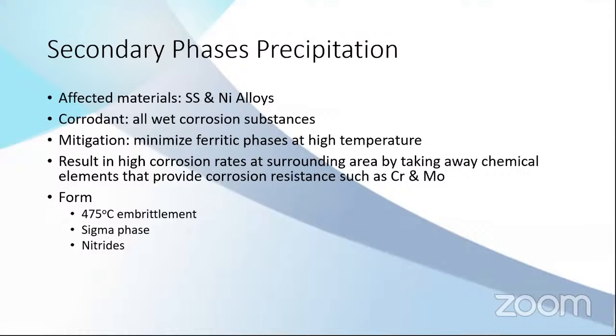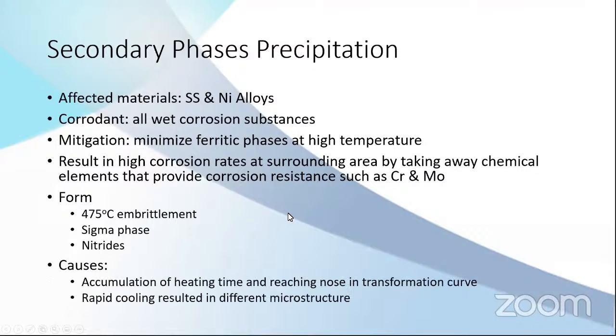And there are many forms of the secondary phase. This is just a generalization. It can be 475 embrittlement. It can be called sigma phase. It can be in the form of nitrides. And the causes are the accumulation of heating time and then reaching the nose in the transformation curve. It's almost similar to sensitization.